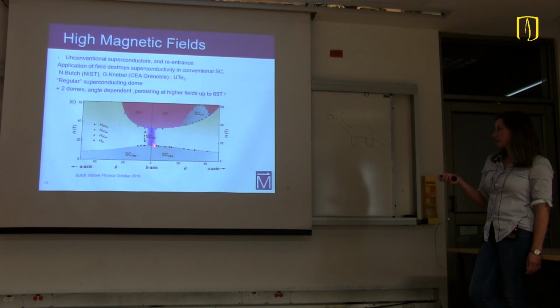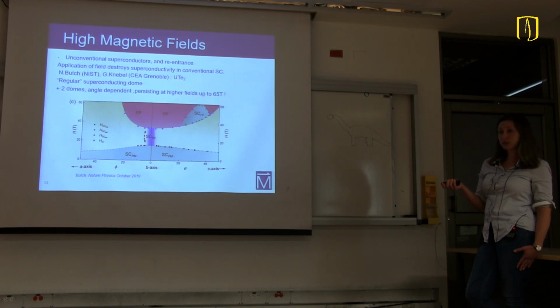So if the axis of the magnetic field is straight parallel to the sample, it was found that there is this general pocket of superconductivity that's then destroyed, but then there is this other pocket of superconductivity that appears and that's reinforced to pretty high, actually, magnetic field here, up to 65 Tesla. So this is like really high.